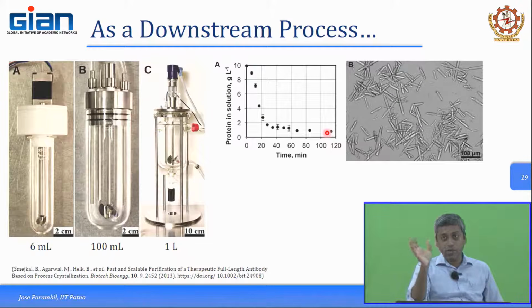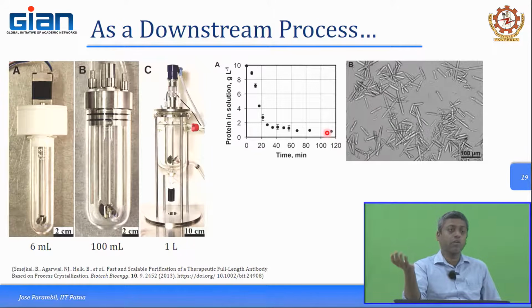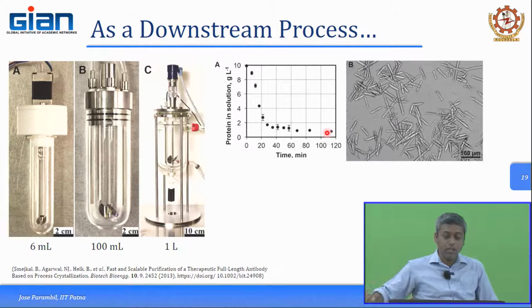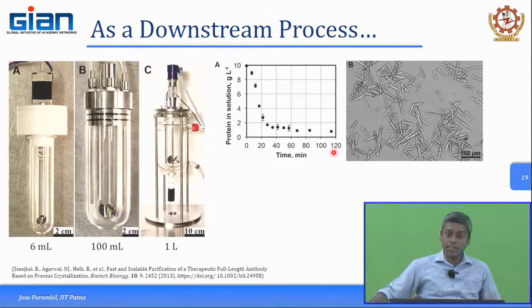Of course, as I told you earlier as well, you cannot ever achieve 100% recovery, because there would always be some soluble component which is left out in the solution. So, that would be a loss, but you can try to minimize that quantity as much as possible, and you can see that this can be achieved within a very short period of time. Within 1 hour or 2 hours, you are able to complete the crystallization process.